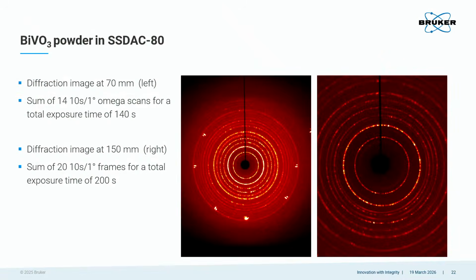People like to do powder and single crystal work. Well, that looks fun. Yeah, you recognize these? Call them Debye rings? Well, I was going to say, you can see that spottiness, which tells us about the texture of the powder or the particle size of the powder. But what's going on with those really big bright spots on the left? Those are the diamond reflections from the anvils. Oh, so this is a high pressure experiment. Yep. So you can get this quality through a diamond anvil cell.